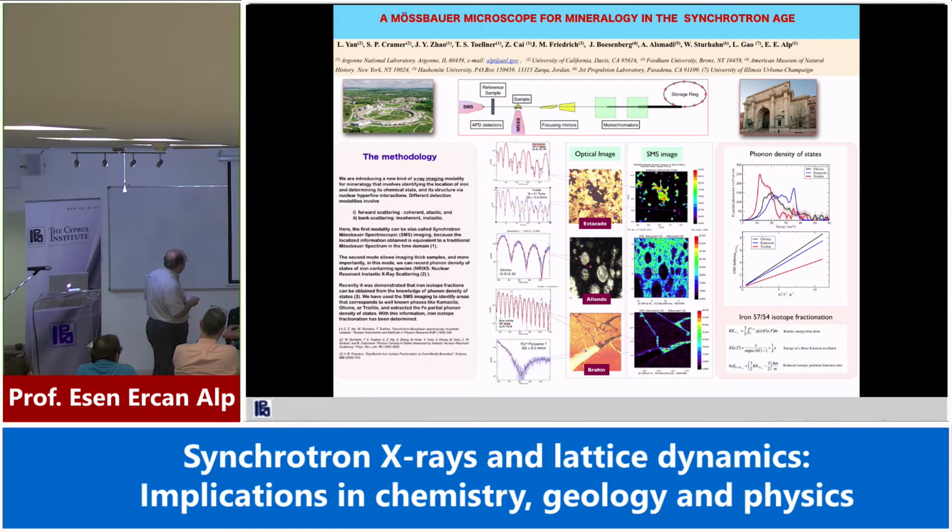So instead of putting the detector in the front, you put the detector on the side and you measure the inelastic spectrum from which you then calculate the force constant. And if you have the force constant, you have the isotope fractionation. Now that's something they cannot do. Because in order to do that, they have to cut this out and make a small sample and then make sure that it doesn't get contaminated with anything, put it into a most sophisticated inductively coupled plasma mass spectrometer, and if they are lucky, maybe a year later they get a number.